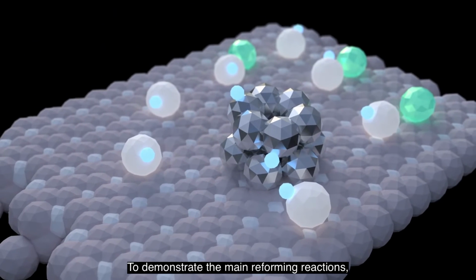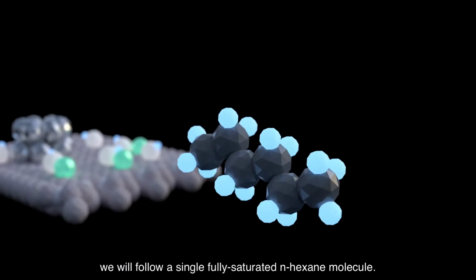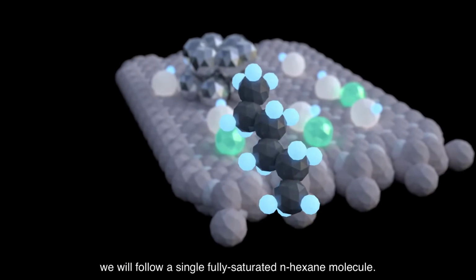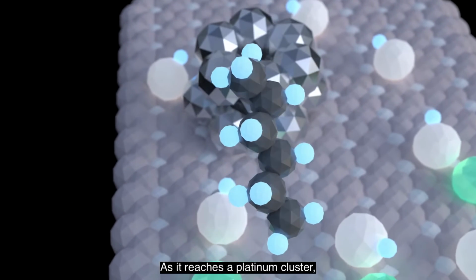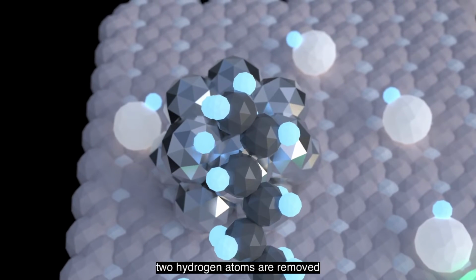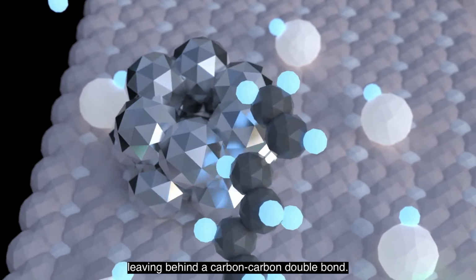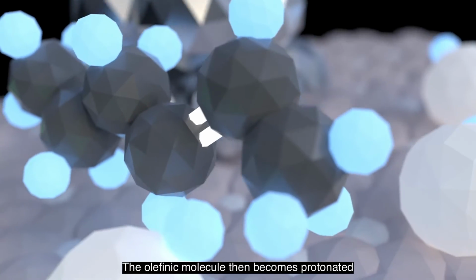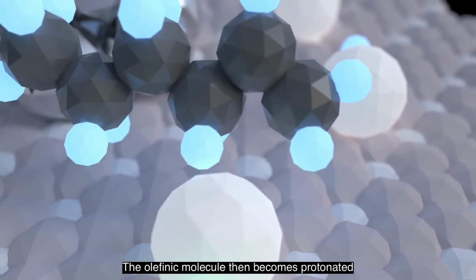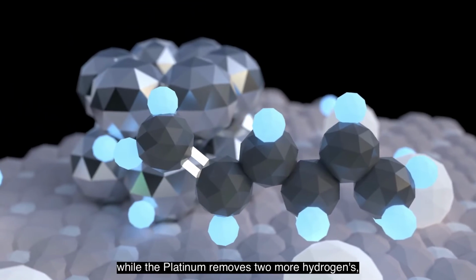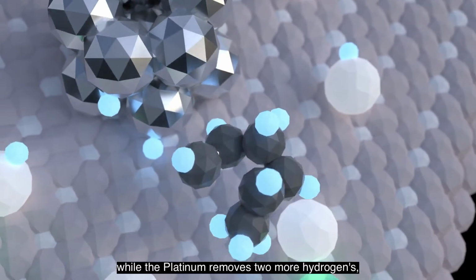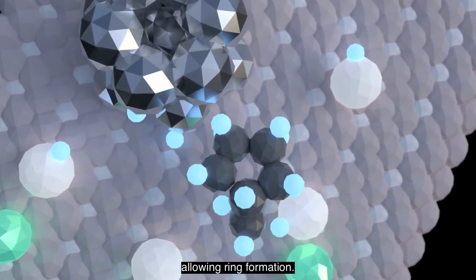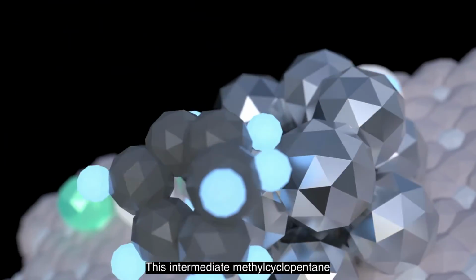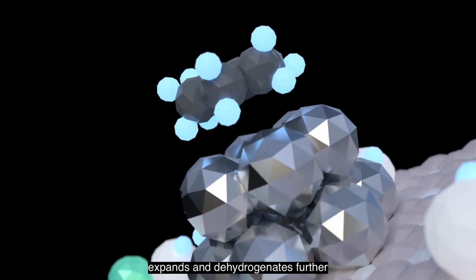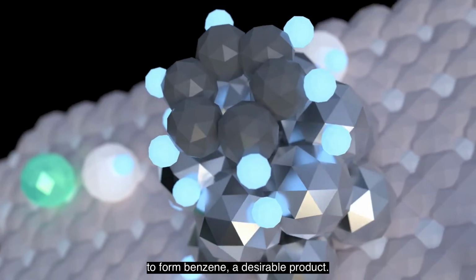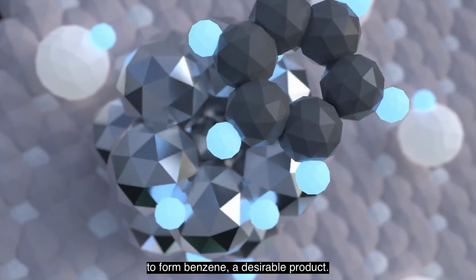To demonstrate the main reforming reactions, we will follow a single, fully saturated N-hexane molecule. As it reaches a platinum cluster, two hydrogen atoms are removed, leaving behind a carbon-carbon double bond. The olefinic molecule then becomes protonated by an acid site, while the platinum removes two more hydrogens, allowing ring formation. This intermediate methyl cyclopentane expands and dehydrogenates further to form benzene, a desirable product.